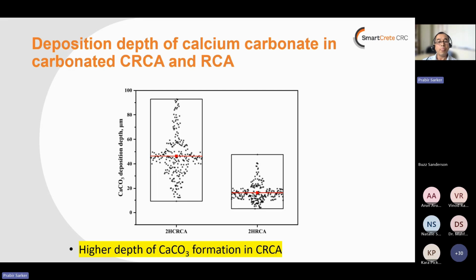Here are some more results presenting the calcium carbonate deposition on the aggregate. And this is the depth of the calcite deposition in the aggregate. This vertical axis is the depth up to which the calcite could be found, and we can see a comparison for 2 hours of carbonation of CRCA here in the left box, and in the right box it is the recycled aggregate concrete obtained from crushing of the cylinders.